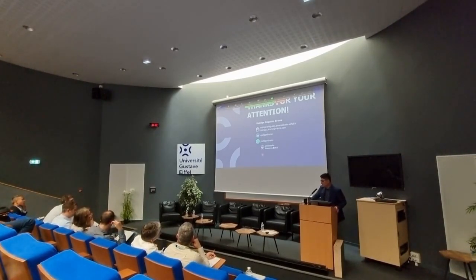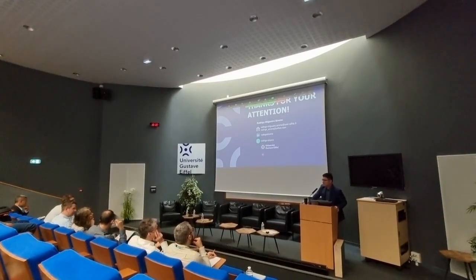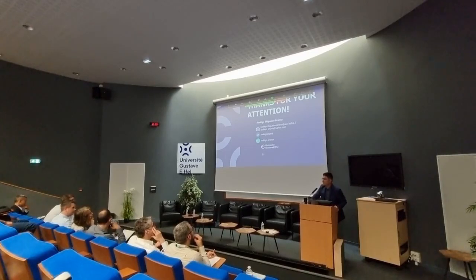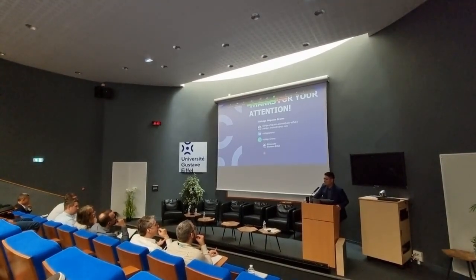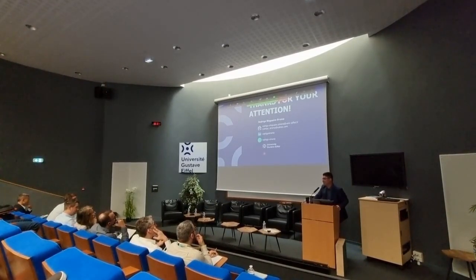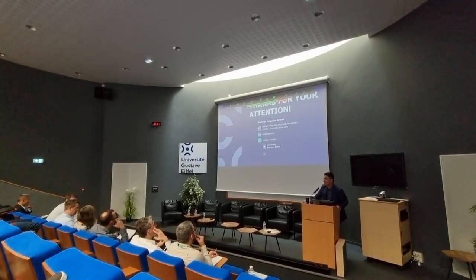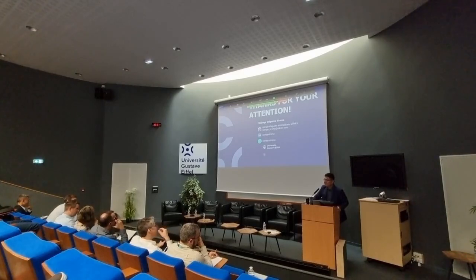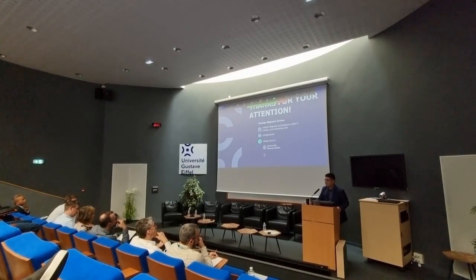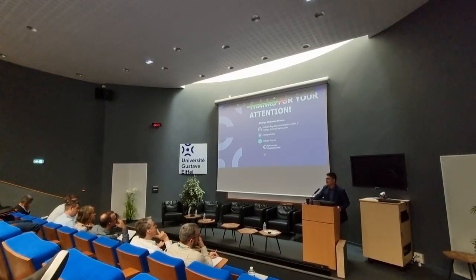This was a very good one. Well, as I mentioned in the presentation, we also perform complex modulus and fatigue tests on our asphalt matrix. And the funny part is, with aging, modulus and fatigue seem to increase. So when we put these increased values in our equations to predict our pavement lifetime, we got a pavement that will last for hundreds of years, which is not real. So that is why we decided to use TSRST, even though it was for base course materials, because at least it's a mixed performance that seems to be more sensitive to the binding effects, to the changes in the binding that is used.